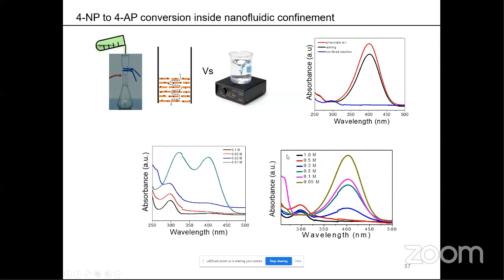Here you can see at different concentrations of sodium borohydride we have tried, where we need a minimum of around 0.1 molar sodium borohydride to do the reaction under stirring condition. On the other hand, in the nanofluid confinement case, the reaction can be done with 0.02 molar itself. That means we need a much lower concentration of sodium borohydride to carry out the reaction. That means the confinement has a huge effect on the way the reaction takes place.